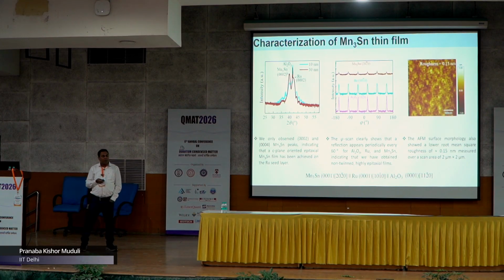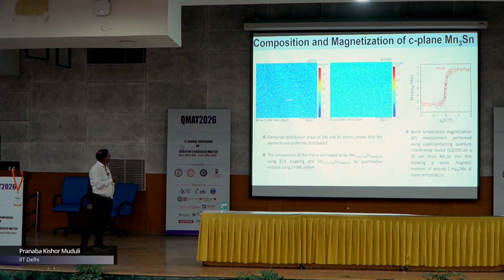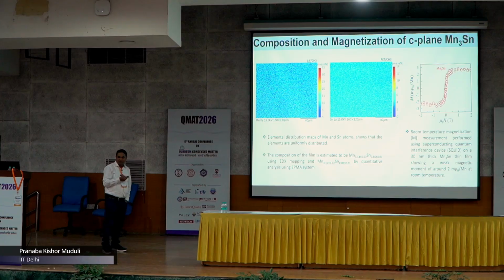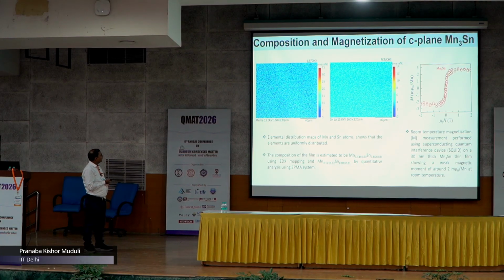Also, we performed composition analysis using EPMA, and we found that we have nearly close to the stoichiometry Mn3Sn, but there is a little bit of excess manganese present, and also the distribution of manganese and tin is more or less uniform. There is not much segregation of manganese or whatever. When you do the magnetism measurement, we do see a little bit of magnetic moment, and this has also been reported in the literature. This is a very small magnetic moment present, because it is not fully compensated, you know.